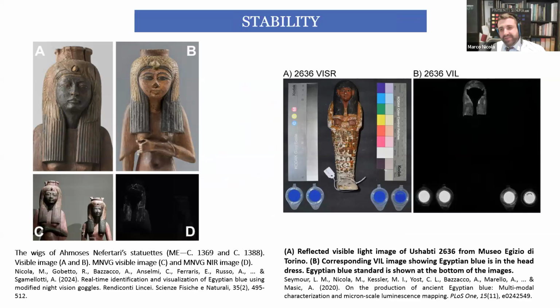Stability. This pigment is very, very stable. So it is luminescent after thousands of years. So this feature of being luminescent is possible to observe even after thousands of years. Obviously, sometimes some change in color is observed, but normally it is not due to the alteration of the structure of Egyptian blue, but to the alteration of the surrounding material. So maybe the binding media that are organic material change their color, and so the general appearance of Egyptian blue can change in tone, and so we can observe a blackening or a turning green, which are the most common alterations. But by itself, the material is very, very stable. And also those changes probably affect not the cuprorivaite, but the glass matrix more than cuprorivaite.